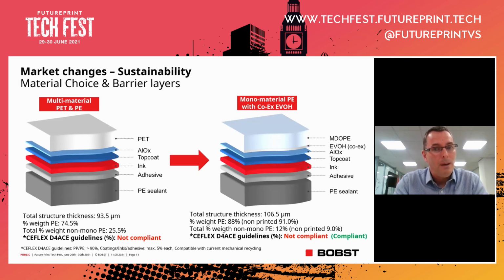This time for barrier, we've added a co-extruded EVOH layer to the skin of the MDOPE. And this is to provide some oxygen barrier coming from the EVOH chemistry itself, but also to provide a metal or metal oxide receptive layer to add on the metallizing step. With this particular structure, the layer thickness and also the polymer or resin densities can be changed or optimized as a way to change the weight percent of the PE monomaterial component. But in general, it's also quite challenging to meet the industry requirements or the industry targets.